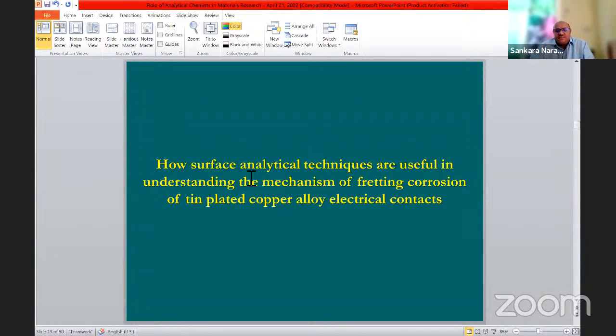And we have studied the fretting corrosion of tin-plated copper alloy electrical contacts. Where are they used? These tin-plated copper alloy electrical contacts are used in automotive materials. Nowadays you might have seen automatic cars, where the dashboard, everything is under automatic electric control. Behind that, there are all these electrical contacts, copper alloy coated with tin. Why coat with tin? Normally we could coat with gold and such, but they are very costly. The simplest solution is plating the copper alloy with tin, because tin is electrically conducting. That is more important. Tin is electrically conducting and it's cheaper.